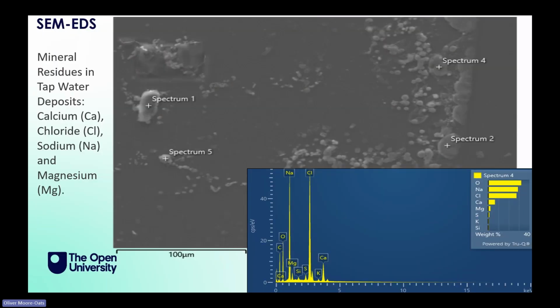Really quick, the first thing we said we're going to do is test it on some stains. On your left side, you can see some watermarks, and on the bottom, a fingerprint. And on the right side, you see the clear surfaces as well. We did some analysis as well. For example, we analyzed the water because it was tap water, and as you know, tap water can contain some minerals. So we did some SEM-EDX analysis. SEM-EDX pinpoints and tells us the inorganic elements. We found that tap water, especially in Milton Keynes, contains calcium, chloride, sodium, and magnesium as well. That means it's really hard water. That's why you see the surface of the water droplet as well.